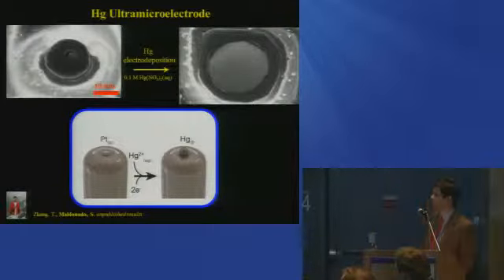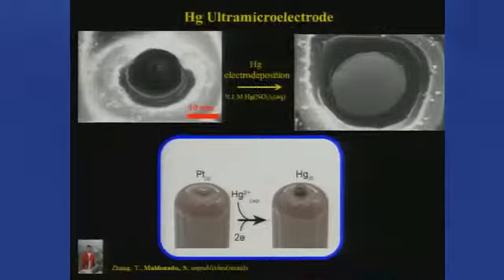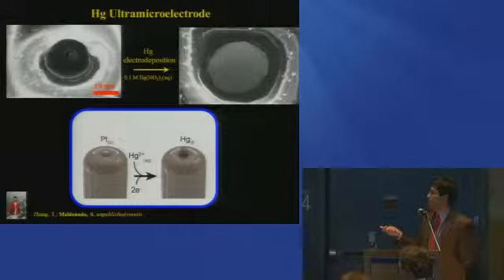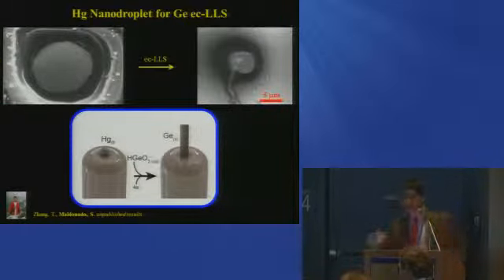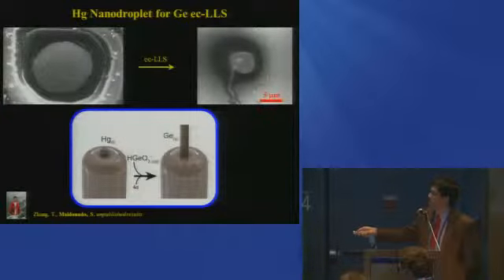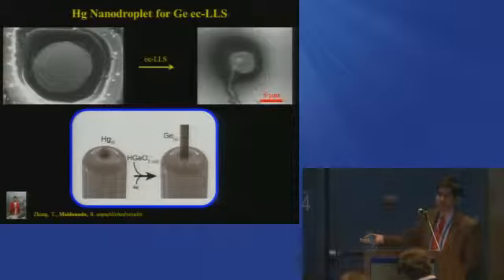So here is one early pass, not that early, but one pass at it. Long story short, because this community should be more in tune with this sort of experiment than others, we made a little liquid metal ultramicro electrode, starting with a platinum ultramicro electrode, depositing some mercury on it. So we basically got a mercury cap. And the idea is that we could use this platform to do the same thing that we did before, but on a localized scale. This is a cartoon describing it. We could use a liquid metal ultramicro electrode to try to electrodeposit through this ec-LLS process a germanium nanowire, maybe one single one.